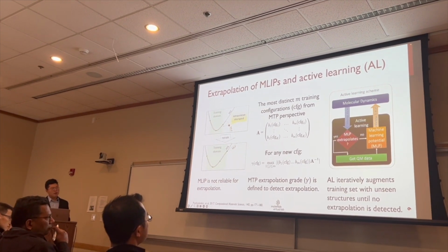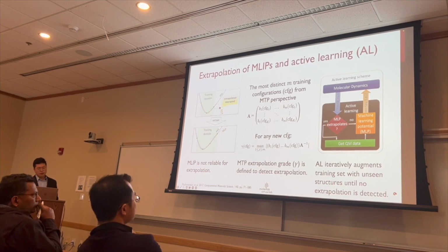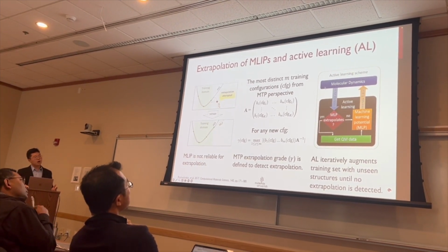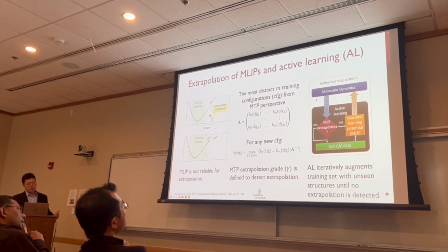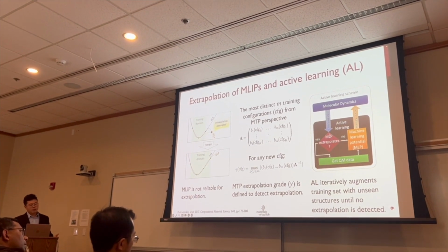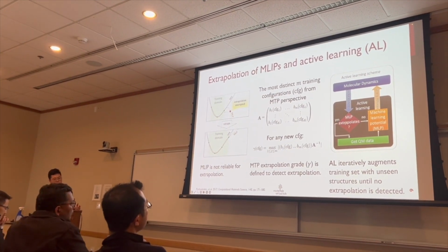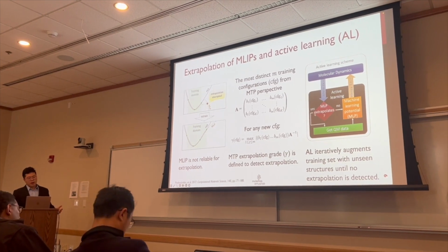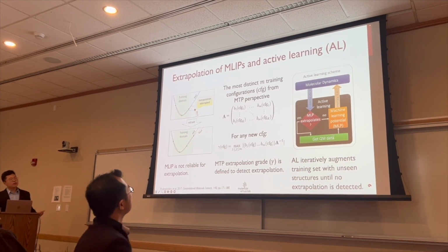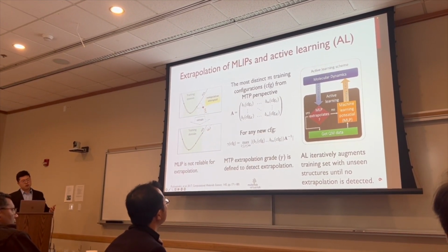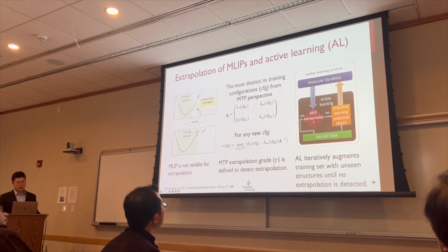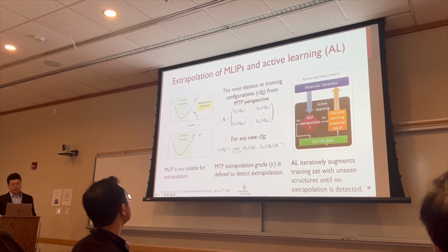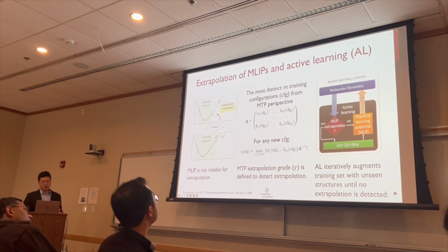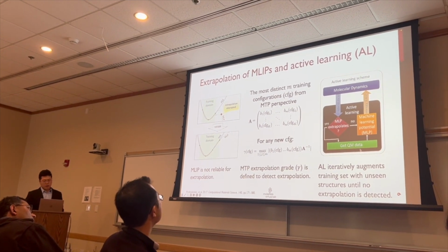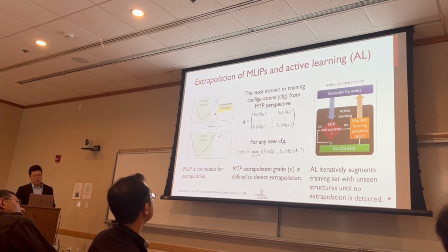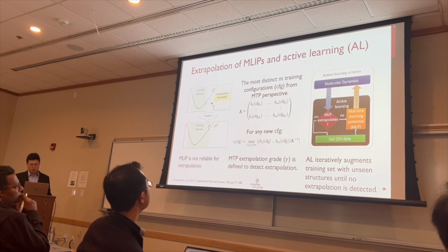So in this workflow, this is a training data sampling workflow, and we start with some pre-trained machine learning interatomic potential to do molecular dynamics on some target simulation scenarios. For every new configuration that emerges in this molecular dynamics simulation, we calculate its extrapolation grade. And if the extrapolation grade is higher than a certain threshold, the MD simulation will be stopped. That structure will be processed by DFT to get the accurate energy and forces, which will be augmented into the training set, and the model will be retrained. So this is a cycle of iterative improvement of the machine learning interatomic potential, and it will end when no extrapolation attempt is detected on that target simulation scenario. So this is a very effective method to collect training structures. However, it can be laborious and time-consuming, especially for larger systems, because of the iterative way of augmentation.